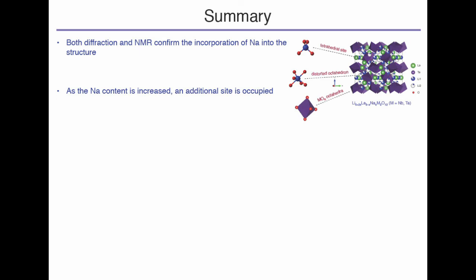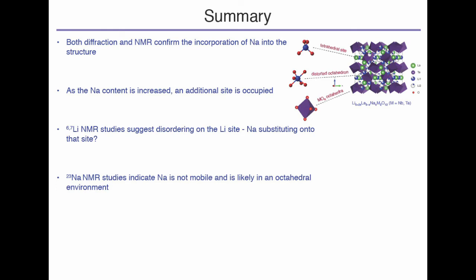It's because sodium has the capability to go into more than one site, which is probably not what happened with the potassium, strontium, and calcium versions, because they're much bigger. So you really need to think about size in this case. But what we do know is that both diffraction and NMR confirm that sodium is definitely in the structure. And as I said, as the sodium content is increased, additional sites are occupied. Lithium NMR suggests that things are moving from the narrowing of the lines, but we do think that the sodium could be substituting onto that lithium site.